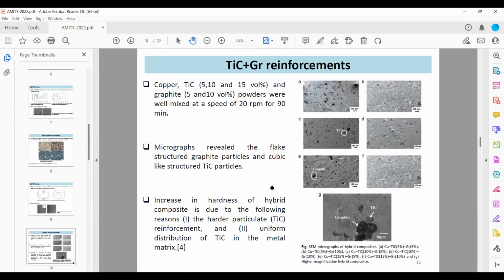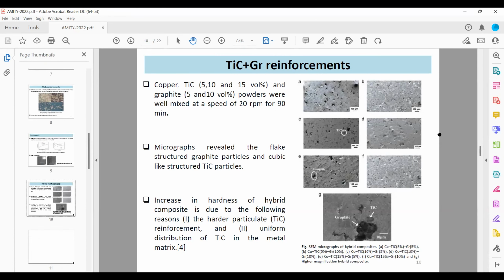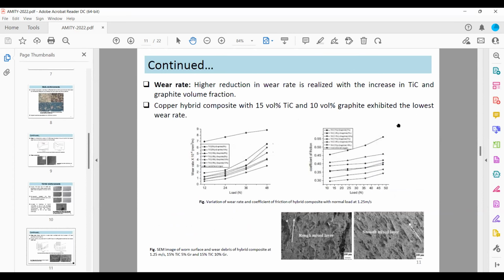Here also the increase in hardness depends on the titanium carbide particles and their uniform distribution, because graphite is a softer particle and it actually decreases the hardness value. The wear rate increases with increase in load. The wear resistance increases along with the hardness, but if the graphite percentage is more, the wear resistance decreases.